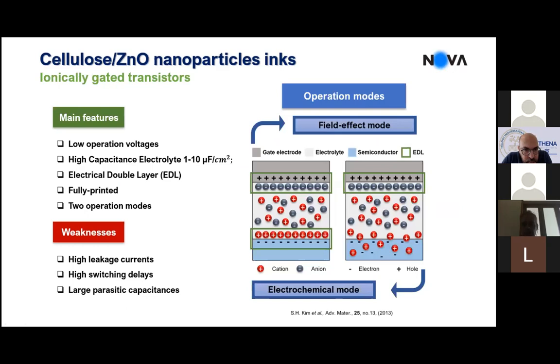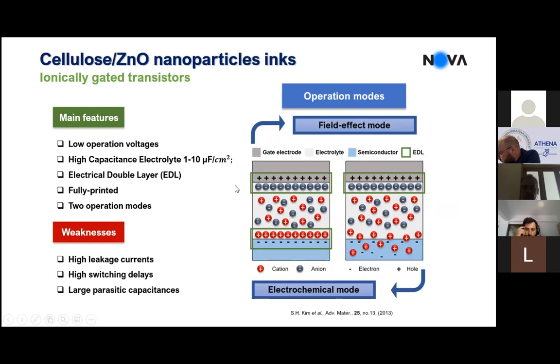Okay, so why do we use these electrolytic membranes? Because if you compare with the conventional dielectric, and you know, for a conventional dielectric, the capacitance depends on the thickness of the insulating material. Okay, and when you use electrolytic membranes, you get rid of this dependence because you have the formation of what we call electrical double layers. So you have mobile ions inside the electrolyte. You can drive these ions. So if you put a positive voltage in what we call the gate electrode, you drive positive ions close to the semiconductor interface.